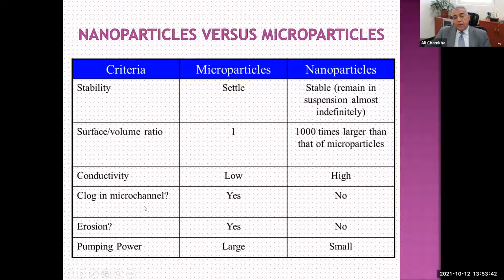The clogging of microchannels, as you could expect: microparticles do clog the channel, while nanoparticles, because they move along the same streamlines of the fluid, do not clog the microchannel. Erosion: because of their weight, mass, and bigger size, microparticles will cause erosion, and nanoparticles do not. In terms of pumping power, it is larger to pump microparticles than you would need for nanoparticles.